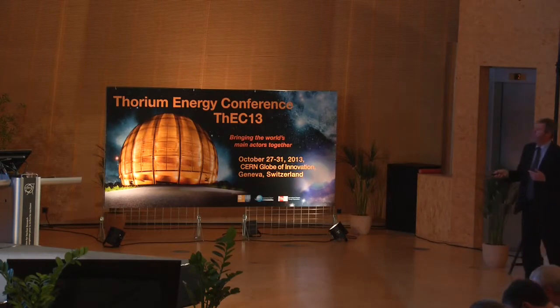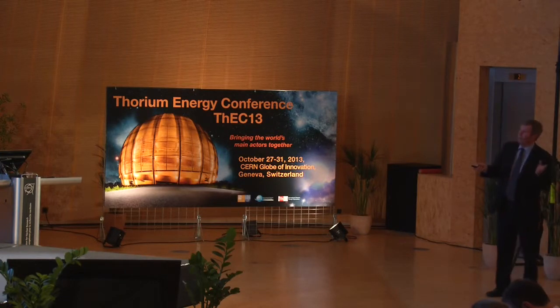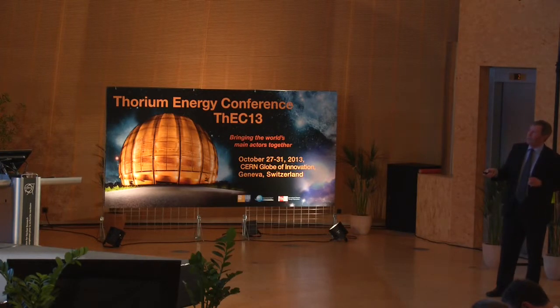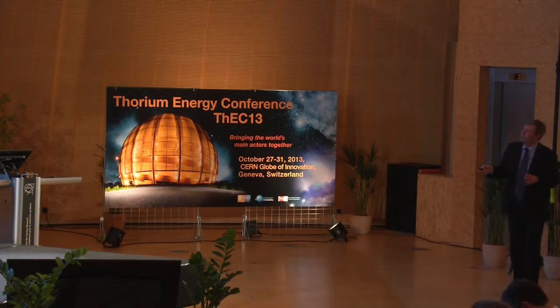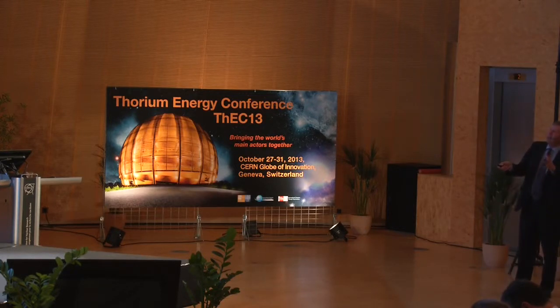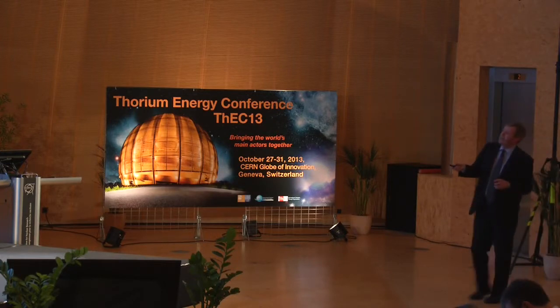And if you go on to change the composition, and so this is the dilute mixture, in fact, which we've just been talking about, 3 times the lithium fluoride to beryllium fluoride, you can see it's a relatively uncoordinated, relatively isolated set of beryllium fluoride tetrahedra.